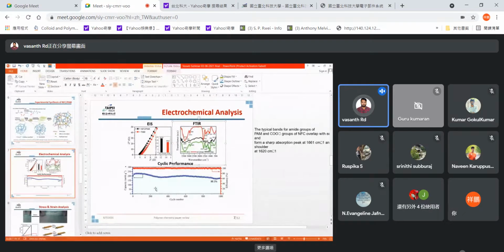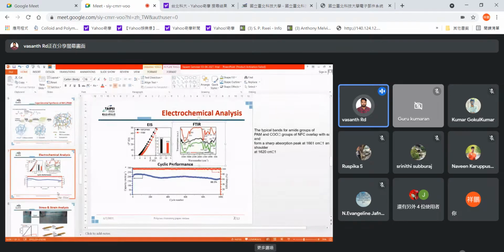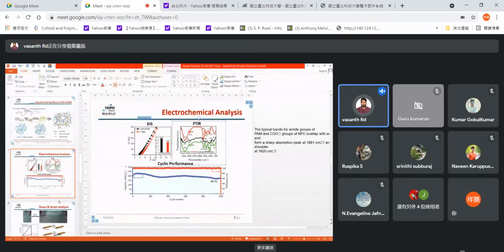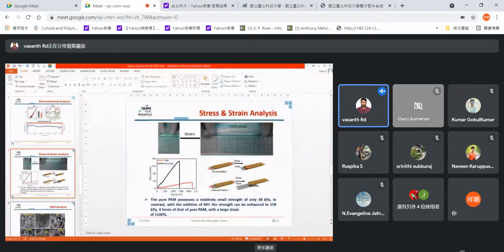And the cyclic performance of NFC PAM is around 88.3%, which is high even over the 1000 cycles. This data is compared between the conventional aqueous electrolyte batteries of ZnMO2, and this is the stress strain analysis which is reported in the paper, in which the pure